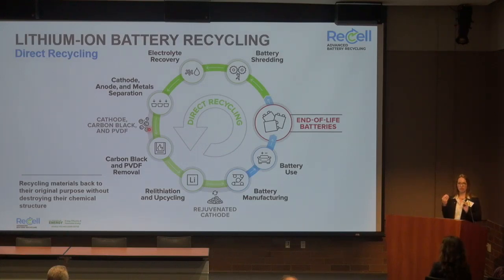When we have our cathode, we still need to rejuvenate that. That mainly means, for sure, relithiation. Since these materials are at their end of life, usually your capacity decreases due to degradative mechanisms of lithium consumption. So they are already at a lithium deficit for reuse. But also through these recycling processes, you can have lithium leaching out of the material. So we take some of the waste streams to then recover that lithium using electrodialysis. So we need to relithiate that material, add more lithium back in, heat to high temperatures, and you have your